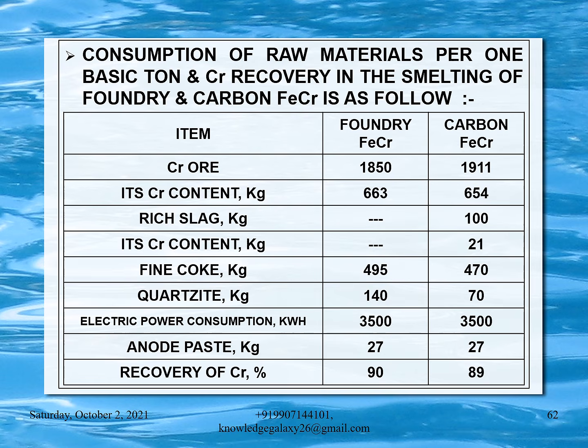Rich slag is not required for foundry ferrochrome. For carbon ferrochrome it requires 100 kg. Its chromium content for carbon ferrochrome is 21 kg. Fine coke: 495 kg for foundry ferrochrome and 470 kg for carbon ferrochrome. Quartzite: 140 kg for foundry ferrochrome and 70 kg for carbon ferrochrome.